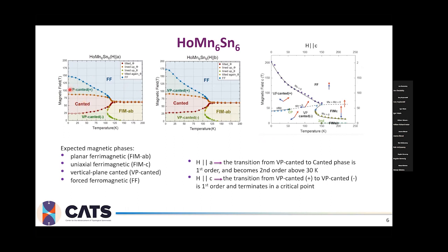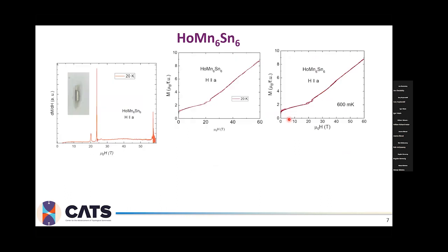There are also some phases predicted at such a high field, which is probably above our current limit to measure. The interesting thing is what actually happens when the magnetic field is applied along the C direction, because it is predicted that the transition over here will end up in a critical endpoint. So with those predicted theoretical phase diagrams, we wanted to check how well they match our experimental data. What we started doing is measuring the magnetization.